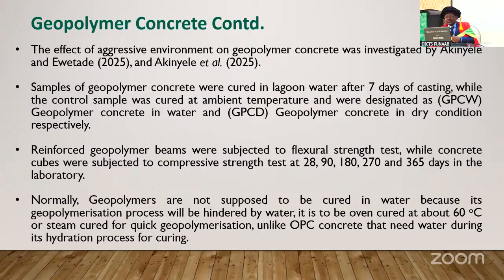The effect of aggressive environment on geopolymer concrete was investigated by Akinyele and Ewetade 2025 and Akinyele et al. 2025. Samples of geopolymer concrete were cured in lagoon water after 7 days of casting, while the control sample was cured at ambient temperature and were designated as GPCW, that is geopolymer concrete cured in water, and GPCD, geopolymer concrete in dry condition. Normally, reinforced geopolymer beams were subjected to flexural strength test, while the concrete cubes were subjected to compressive strength at 28, 90, 180, 270, and 365 days in the laboratory. Normally, geopolymer is not supposed to be cured in water because its geopolymerization process will be hindered by water. It is to be oven cured at 60 degrees Celsius or steam cured for quick geopolymerization, unlike ordinary Portland cement concrete that needs water during its hydration process for curing.